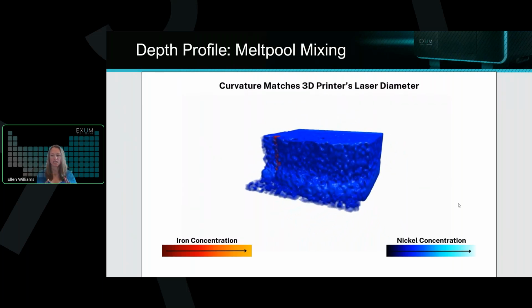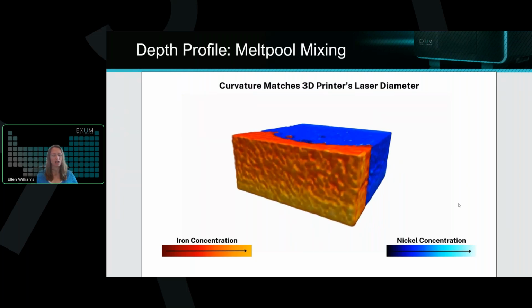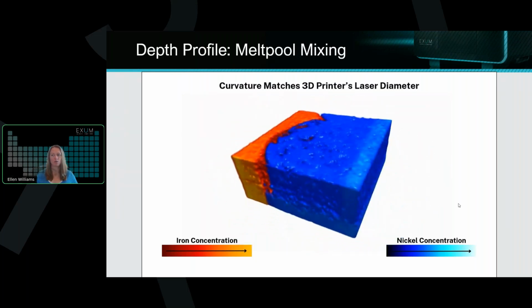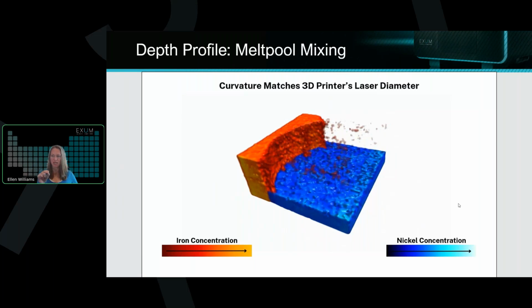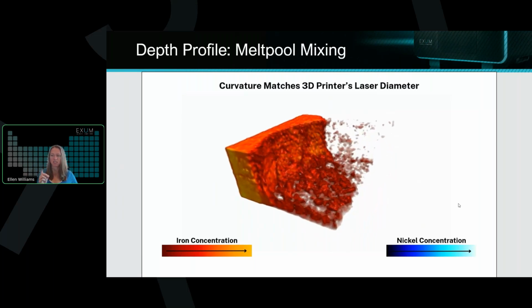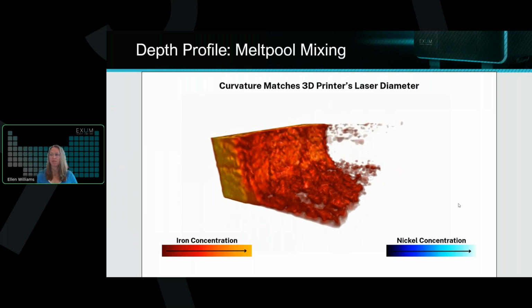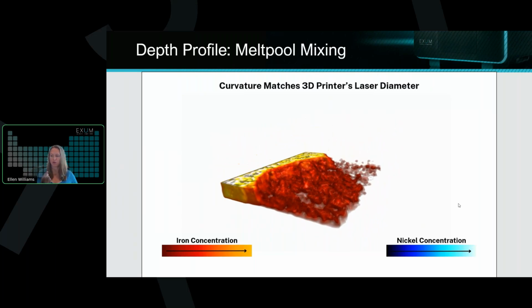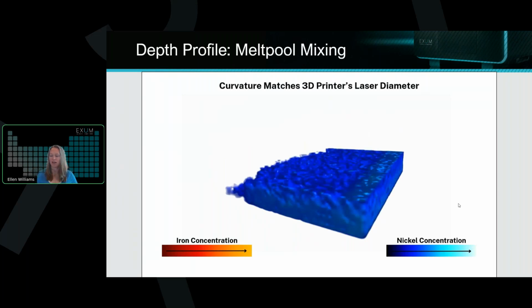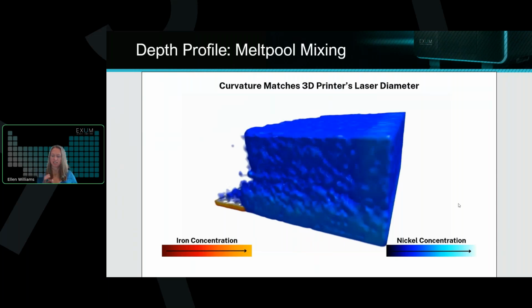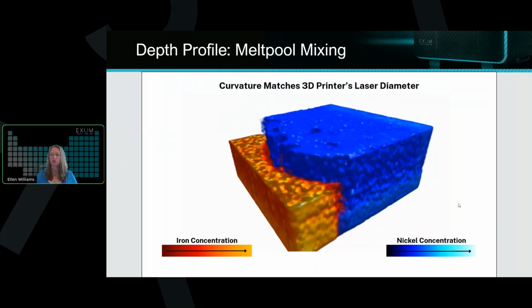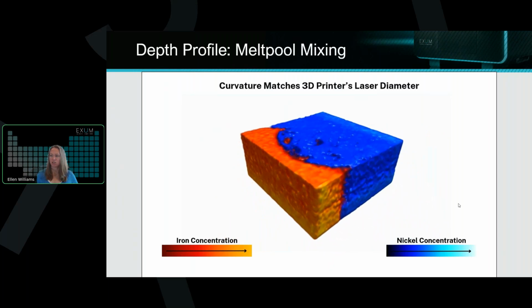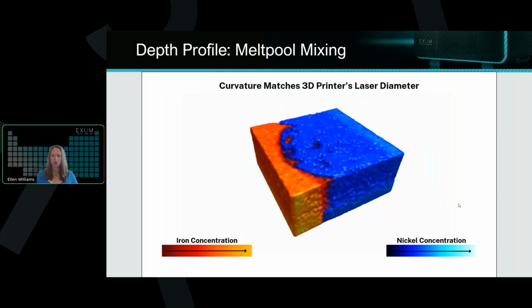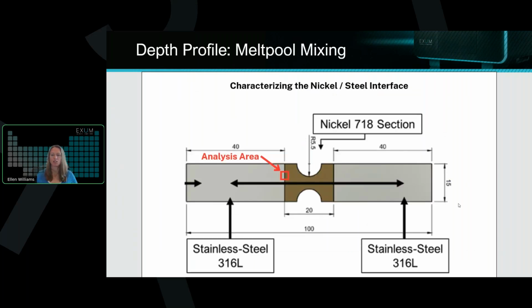And then we're visualizing how the iron and nickel concentrations change in 3 dimensions. So once again, we can see those defects created by the Marangoni flow that are going around that melt pool, that curved area. And we can see how that changes from the surface layer to below the surface. So again, a really impactful modality and ability to see not just how elements change in the XY direction, but also how they change in depth.